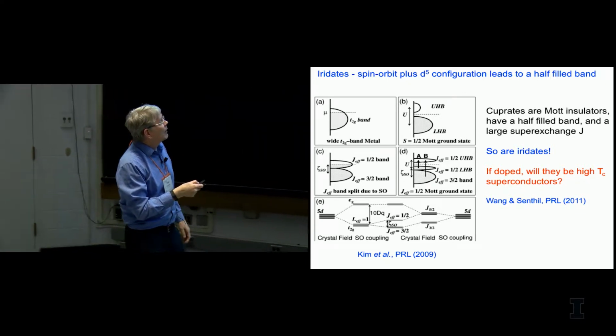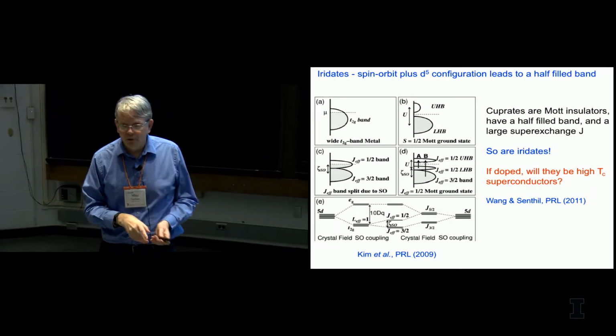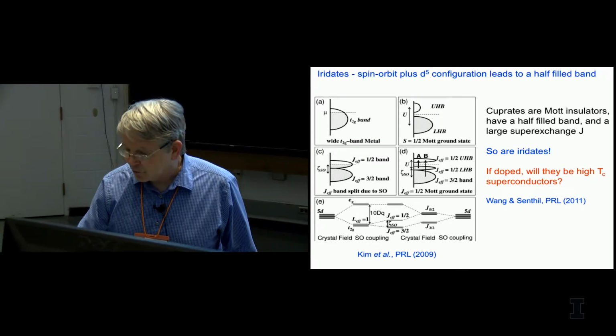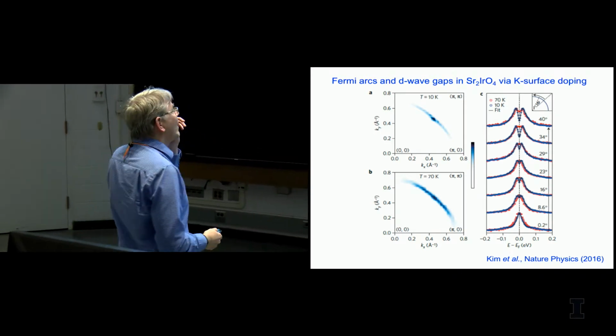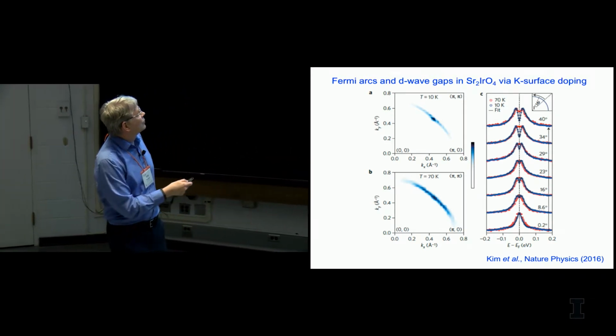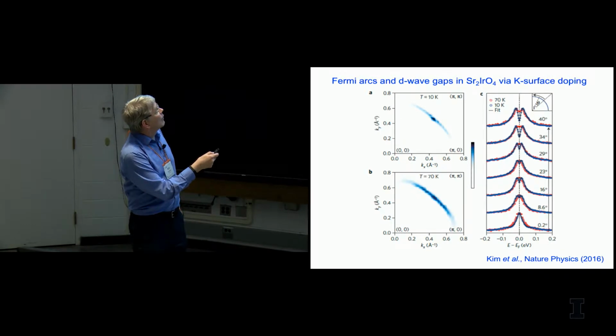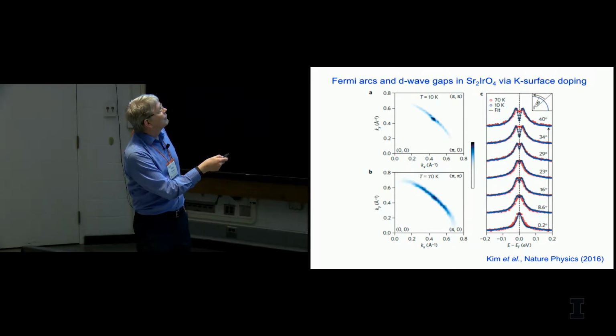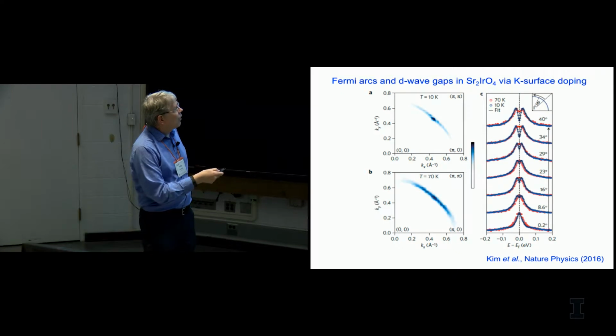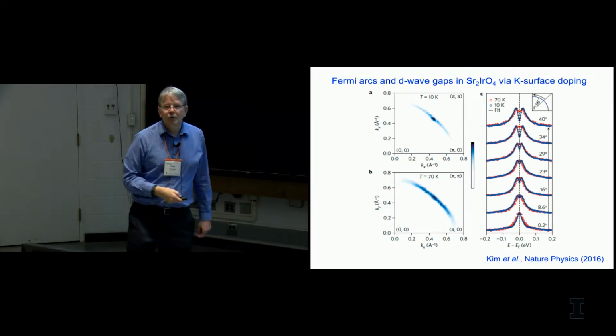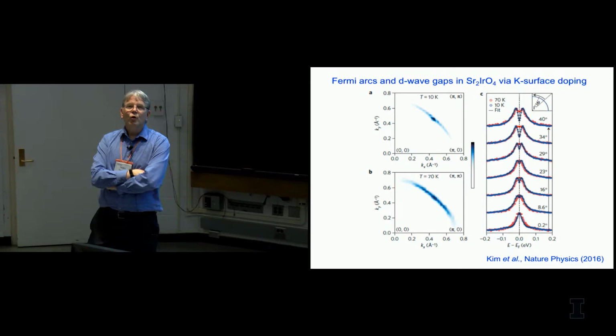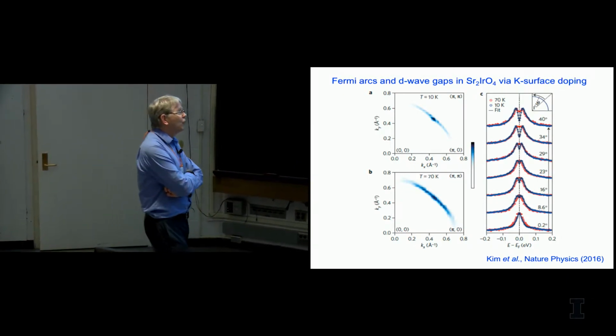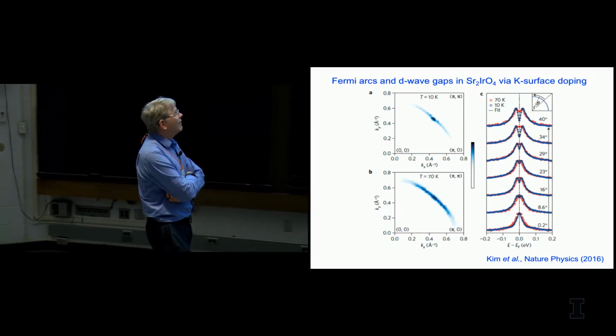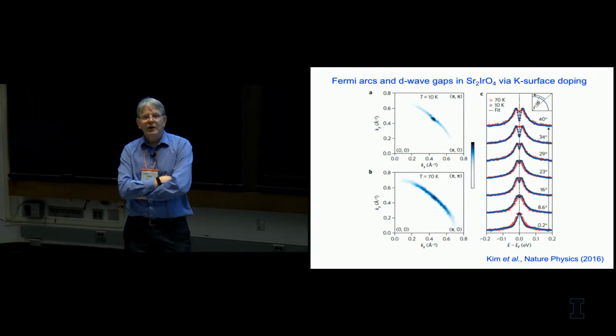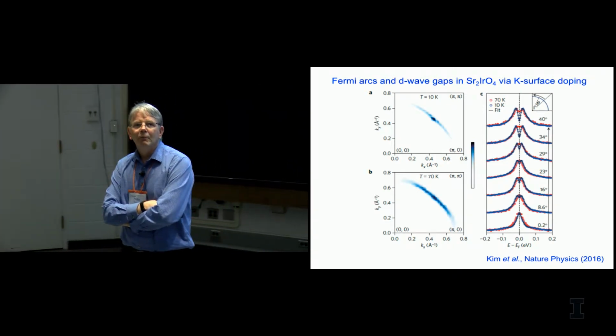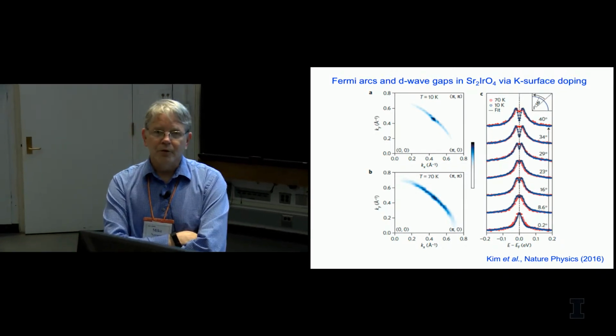Still, there were a lot of speculations by people like Senthil that they might be superconductors, and although superconductivity hasn't been seen, one does see pseudogap-like phenomena very similar to cuprates, including Fermi arcs that at low temperatures seem to go into a d-wave node. So although so far this class of materials is not superconducting, it does have pseudogap-like effects to it. So we're still searching for a cuprate analog. We haven't found one yet, but I think we're probably pretty close to getting one, and we think that if we can find it, it might tell us a lot about what's going on in high-temperature superconductors.